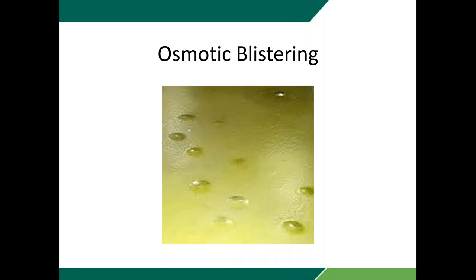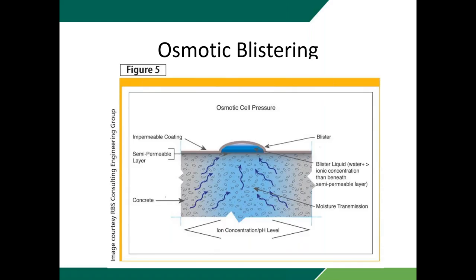When we put down impermeable coatings such as epoxies and urethanes and things like that, it's not uncommon, if we've got moisture coming up out of the concrete, to get blistering. And this blistering is typically osmotic blistering, in which an osmotic cell gets created beneath the coating at the concrete interface, and it builds up a great degree of pressure. It's been tested to show that through osmotic blistering we can get pressures of upwards of 300 to 400 psi, far exceeding the bond capacity of most of your epoxy and urethane coatings.